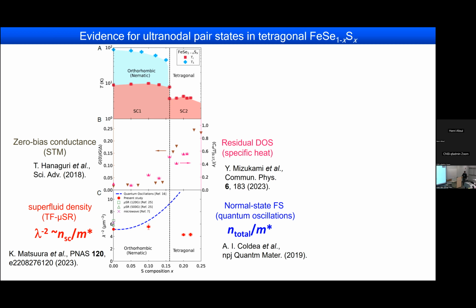And then there is another experiment which has been done, which is the transverse field μSR, from which we can measure the superfluid density, which is 1 over the penetration depth squared. This is related to the ratio between the superconducting electron carrier density divided by effective mass. And this is plotted by these red dots, which can be compared to the normal state n over m star, in which n represents the total carrier density. This can be estimated from the quantum oscillation measurements, which is plotted by this blue line.